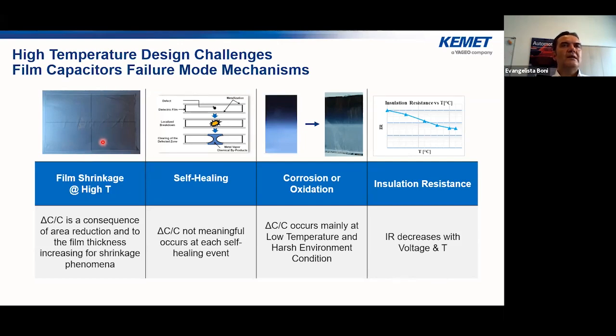And when it is submitted to temperature, the film tends to return to its original thickness. So it shrinks, reducing the area and increasing the thickness, and therefore causing a slight capacitance drop. Later on, the second point is the self-healing of the capacitor.